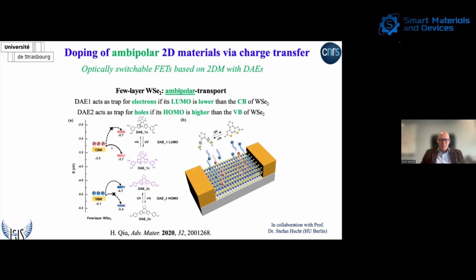So we can use the very same molecule for this, but we can also have a second molecule that is interfaced at the same time to the tungsten diselenide, which is another derivative of the diarylethene that by design has a HOMO level that falls in the band gap of the tungsten diselenide when it is closed, and when it is open, it falls out of the band gap. And so we are trapping and untrapping the hole conduction. This kind of energetic level consideration has to be done by considering, in this case, the position of the valence band of the tungsten diselenide.